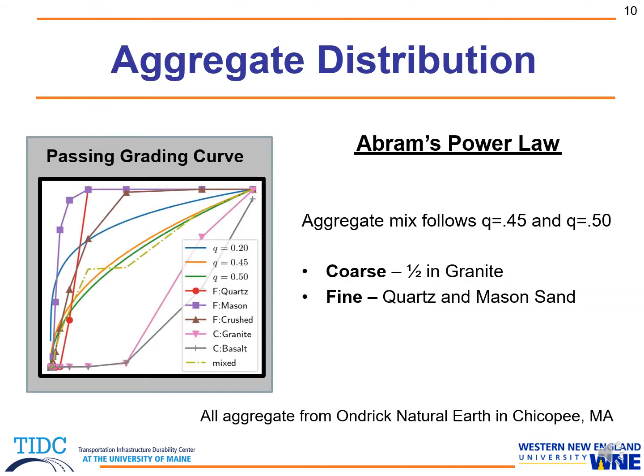The aggregate distribution was calculated using the Abrams power law. On the left is the diagram of a passing grading curve where Q of 0.45 is in orange and Q of 0.5 is in green. The yellow dashed line is our mixed aggregate. So it follows Q of 0.45 and Q of 0.5 very, very closely.